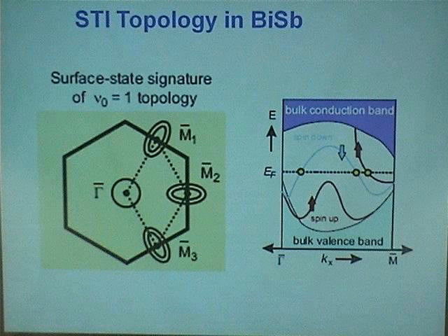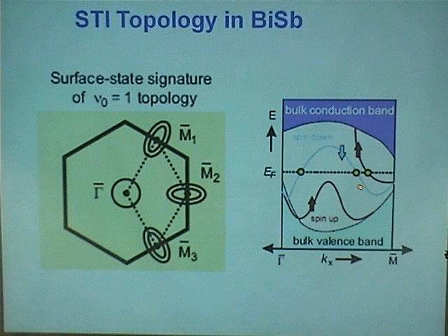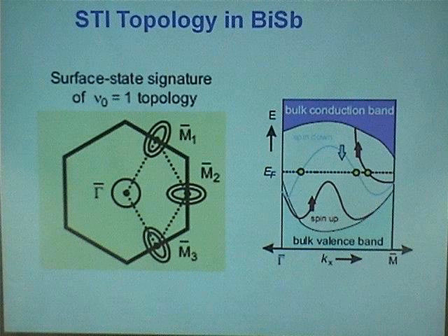The other possibility is that it goes up and has to hit somewhere. And as I showed, because of time reversal invariance, it must meet at M with another band, because it has to be degenerate there. And as I showed, just by doping the surface you can get rid of the 2 states because they're trivial. So I'm left with these 2 options.